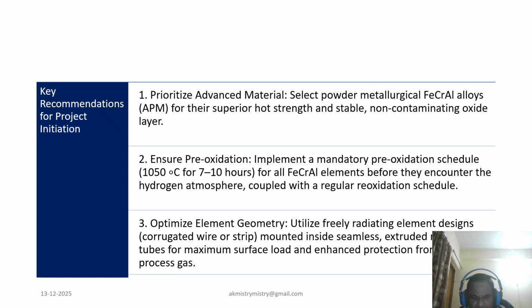So, to summarize our key recommendations for a successful high temperature hydrogen heating project: first, prioritize advanced material selection. Choose powder metallurgical ferrochromium aluminum alloy APM for its superior hot strength and a stable, non-contaminating oxide layer. And in addition to this, APMT can be selected, where some molybdenum is participating, which is much better for withstanding creep, and yield strength is also higher. So APMT is much better.